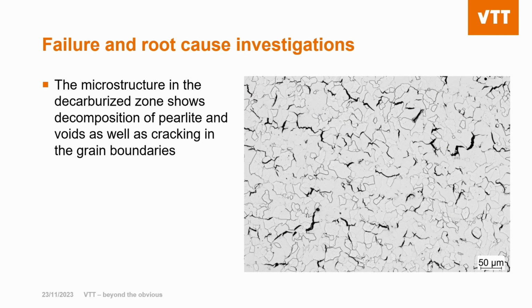The microstructure in the decarburized zone shows decomposition of pearlite and voids as well as cracking in the grain boundaries. So if we look at the microstructural image here, we see that all the darker pearlite or bainite grains have converted into ferrite, and we can also see numerous cracks in the grain boundaries originally due to the methane bubbles.